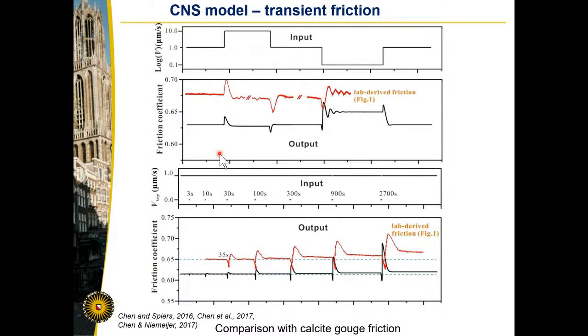Can we reproduce our laboratory data? Yes, we can. We can actually use this model to simulate our velocity stepping scheme. In red here is some calcite data from Chen, and he simulated this experiment. And you can see we see an increase in friction and then an evolution to a new steady state. If we change the step, we get a different response. We can also simulate the healing that occurs during these slide-hold-slide experiments. So that is what is shown here. And that fits really quite nicely.